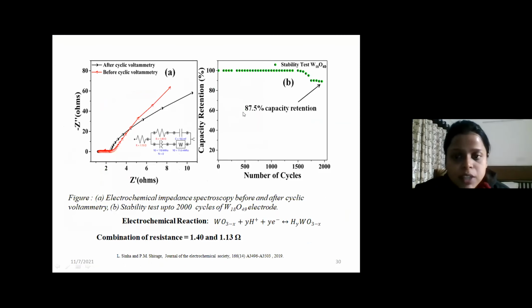Now we have done the stability test and impedance spectroscopy for knowing the resistance in the material, and it is 1.40 and 1.13 ohm. This we have done from the circuit fitting model analysis, and we have also conducted the stability for 2000 cycles, and this is showing the capacitive retention is 87.5%.